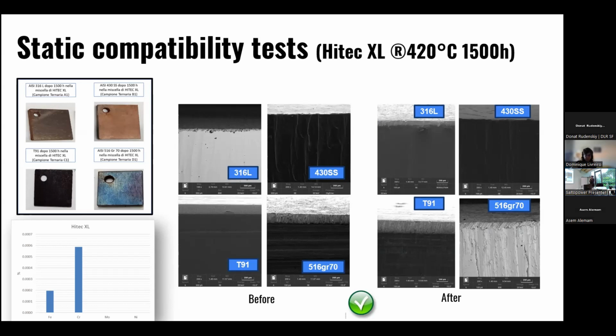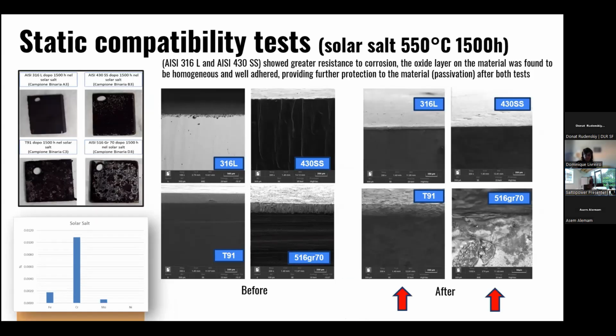And here are the pictures of the 4 steels that we inserted, and the same analysis before and after the static compatibility test. This first test was performed with HitecXL at 420 degrees, and you know that the corrosion mechanism is very difficult to explain in only a few minutes, but what we are looking at is the passive oxide layer that forms during the corrosion experimental campaign. As you can see, before and after, the layer is very compact and there are no damages or no holes in this layer. So we can state that for now this test was okay,